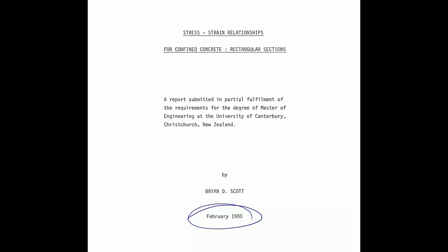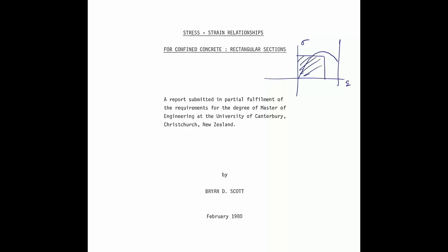So the use of the proper concrete model will enable us to see the moment-curvature response of the reinforced concrete cross-section. The Whitney stress block is for that ultimate state where the concrete reaches this parabolic stress-strain relationship. That stress-strain relationship was simplified by this concrete stress block. It is applicable to just that. Somewhere in between, let's say if your cross-section develops this, you cannot use that Whitney stress block, right? This is more or less like a triangular distribution than the rectangular stress block distribution.